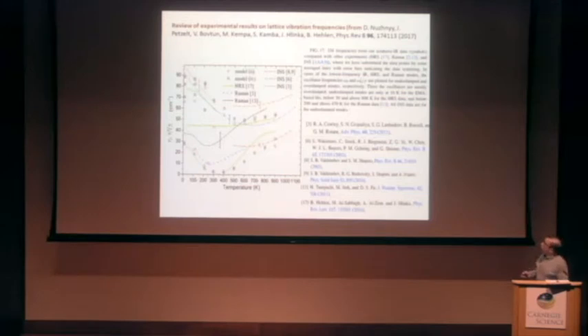And here I show the picture borrowed from this recent paper, which summarizes all the most important experimental investigations, and shows the frequencies of low-lying optical transverse lattice modes. And you see that the points are everywhere. Thus, all the space of temperature and frequencies is filled by experimental points almost homogeneously. Many experimental techniques like inelastic neutron scattering, Raman scattering, and infrared techniques measure the properties only in some particular intervals of frequencies, temperatures, and so on.